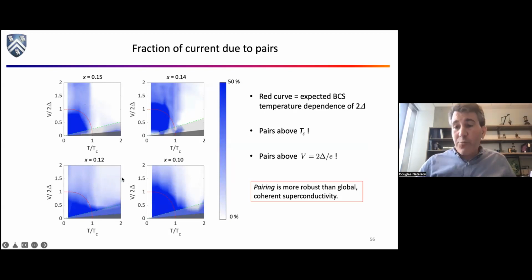And this was, again, very surprising and very interesting to us. I think it tells you that the pairing of the electrons, the electrons not acting like individual electrons anymore, the pairing is somehow more robust than superconductivity, right? When you go above TC in one of these materials, superconductivity dies, but the pairs don't. It doesn't die because the pairs fall apart, which is what happens in something like lead. It dies because somehow the coherence, the ballet dance of all the pairs together, stops.